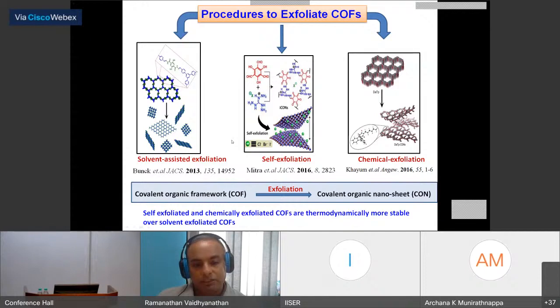So there are different methods to exfoliate a COF. You can exfoliate it by solvent-assisted sonication, or you can have a very smart way of using one of the monomers to be non-pi stacking. Then naturally, the pi stacking is weaker. Then even during synthesis, the COF can occur as polymers, which are self-exfoliated. And that is another approach. And then the third approach, which is a more controlled and robust approach, is to chemically introduce functional groups, either post-synthetically or during the synthesis, which do not favor pi stacking but keep all the aromatic richness of the COF, and then form an exfoliation in a very controlled manner.